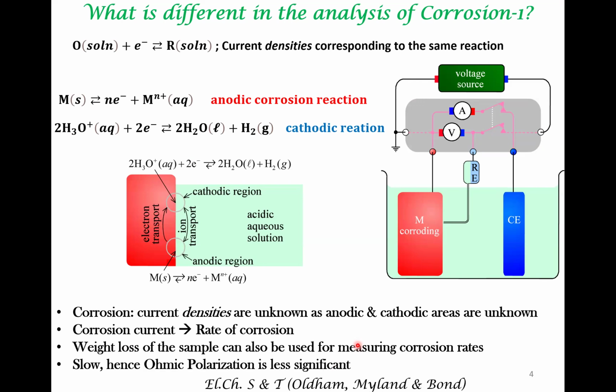And it's also important to understand that the ohmic polarization is less significant in all corrosion studies. Okay, there are different ways to think about this. Ohmic polarization is associated with IR drop. So I is relatively small in corrosion, and R is also less due to some reason. For example, the electron transfer here is very facile, and the ion transport can also be facile because the anodic and cathodic regions can be near to each other. Because of all this, ohmic polarization is less. So these are some of the factors that make corrosion different from the study of electrochemical kinetics of this kind of reaction.